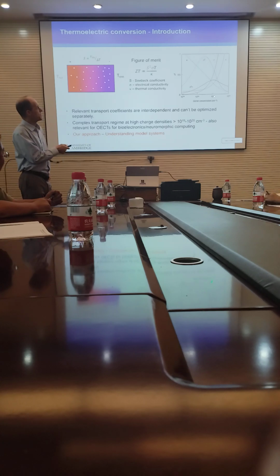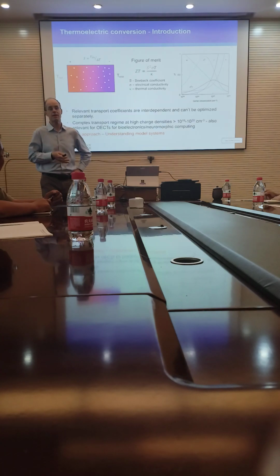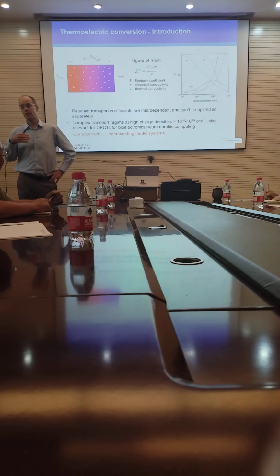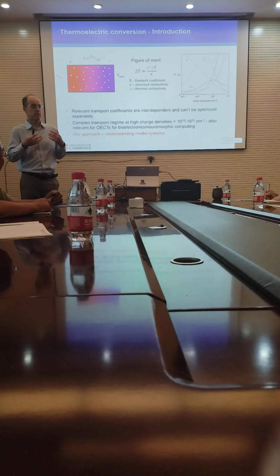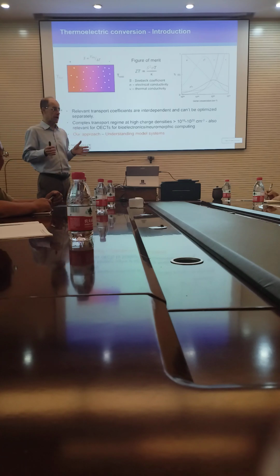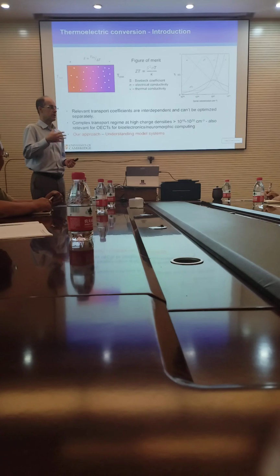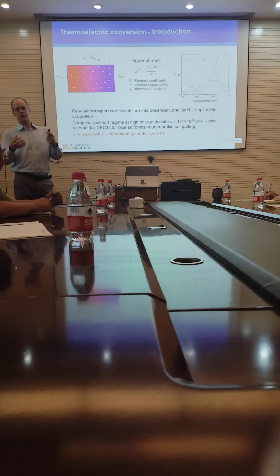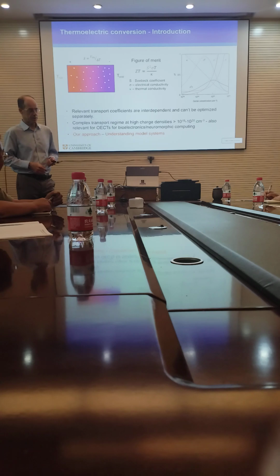And that typically gets you into a regime of carrier concentration 10 to the 19, 10 to the 20, maybe 10 to the 21. So the carrier density in these thermoelectrics is really high, and you're really bulk doping the material to carrier densities that approach the limit of 1 charge per monomer. And so we got interested in understanding the charge transport in this regime.